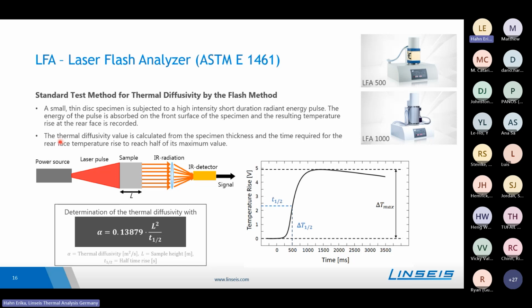The laser flash setup is a standardized test method according to this ASTM norm for the determination of the thermal diffusivity. For the test, a small and thin specimen is subjected to a high intensity, short duration radiant energy pulse, and the energy of the pulse is then absorbed on the front surface of the sample and distributes in there, and the resulting temperature rise at the rear face is recorded. So this is illustrated here. We have a power source, which is in our case either a xenon lamp or a laser source. We have the sample and an infrared detector on the right side of that to collect the signal.